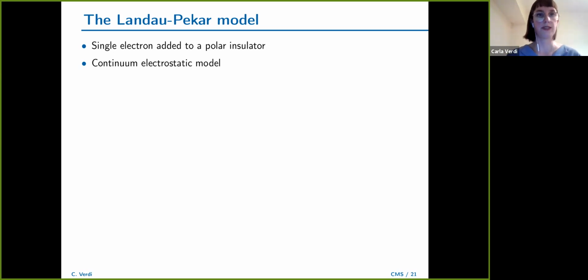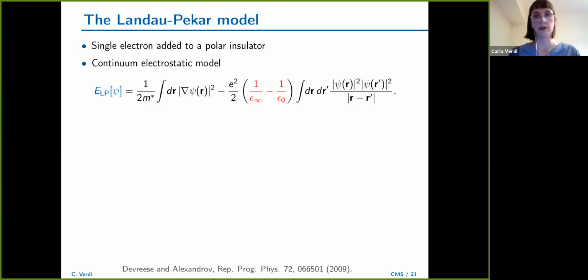Now, this model deals with a single electron added to a polar insulator. And so this electron travels in the crystal, and because of these electrostatic interactions, it might get self-trapped. So it is a continuum model, meaning that the polaron is assumed to be extended and to be large enough that the atomistic details don't matter. Then it is actually quite easy to derive this expression. This is the total energy of the Landau-Pekar polaron as a function of the polaron wave function psi. So you see there is a kinetic term. Here the prefactor includes an effective mass that effectively deals with the interaction of this extra electron with the electrons in the crystal. And then this is the electrostatic part.